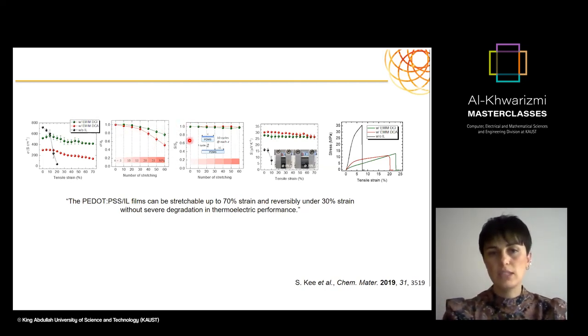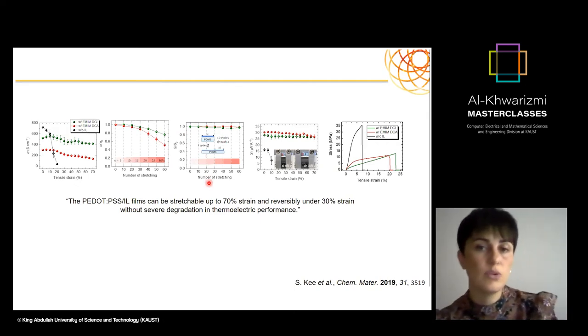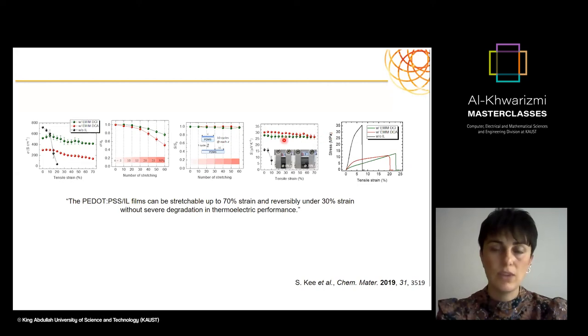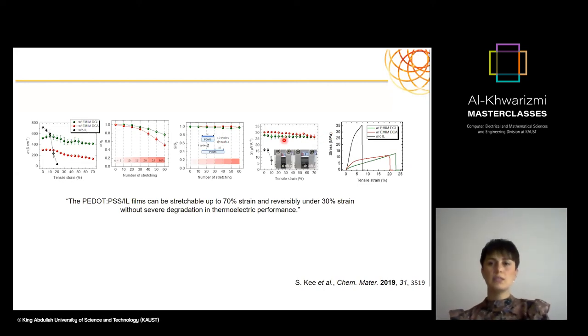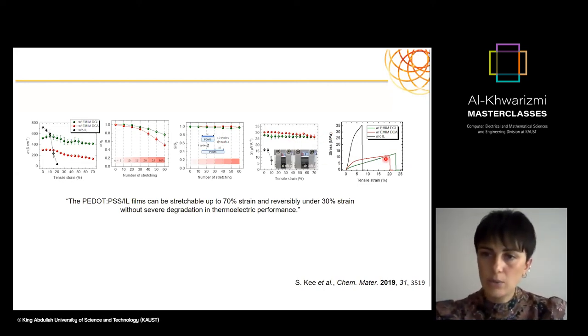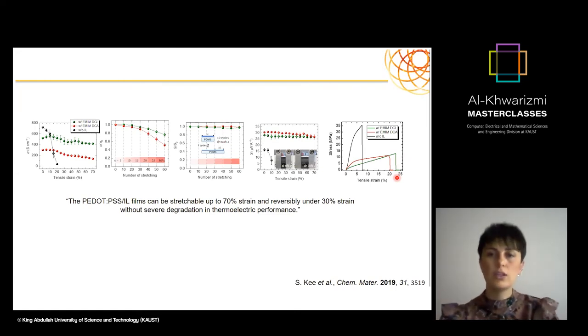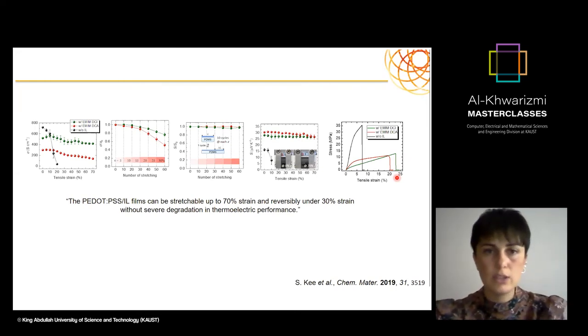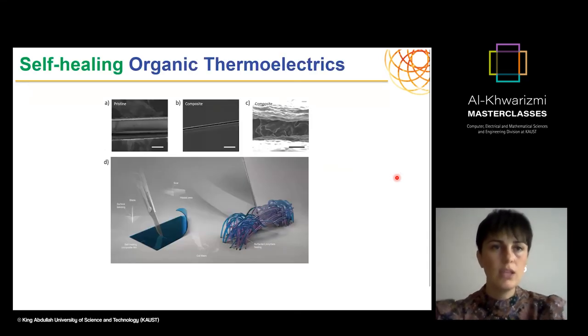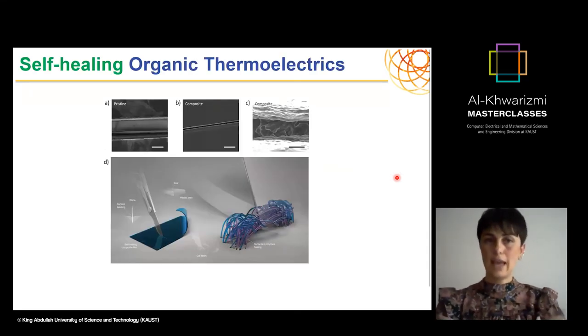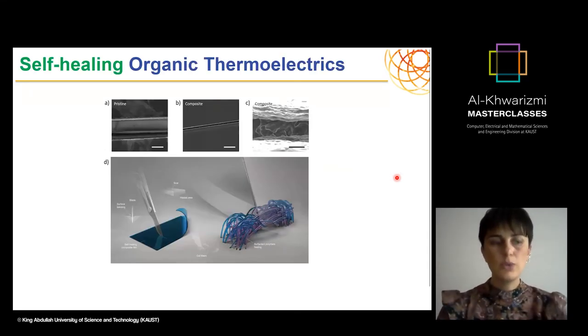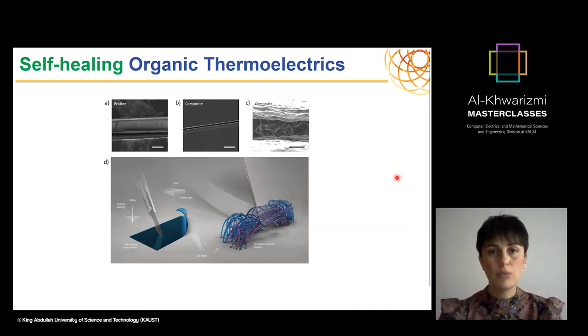And then you can do the same thing for the Seebeck coefficient, as I said, which is also another important parameter, and both the Seebeck coefficient and the conductivity showed relatively reproducible results. And then in the end, we were able to apply this strain for the whole ionic liquid added thermoelectric devices. So then we thought, okay, this is good. Now we can have it stretchable. So could we then add further self-healing property?